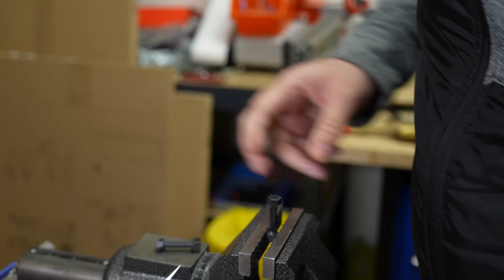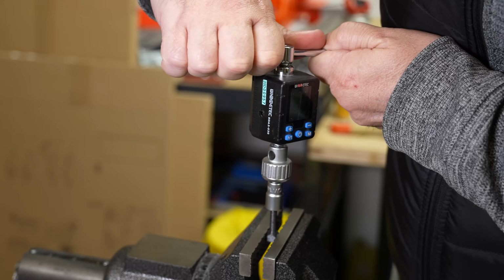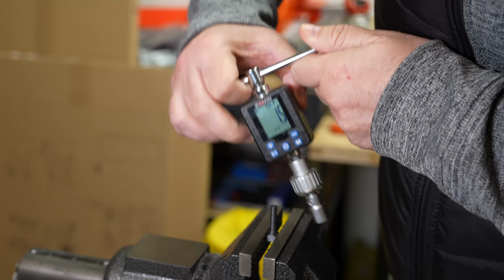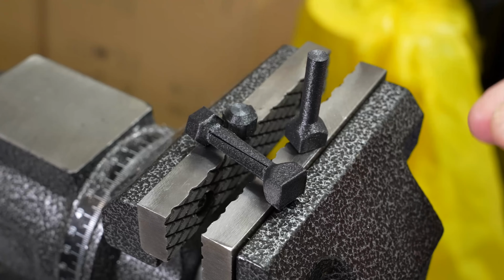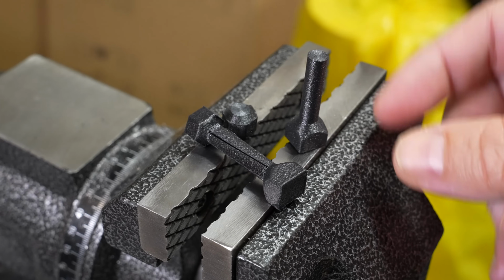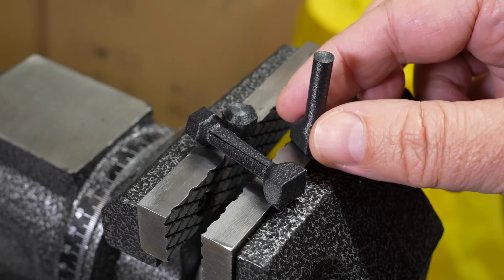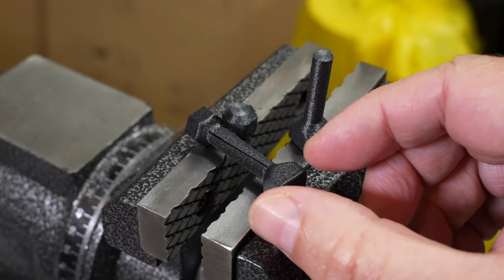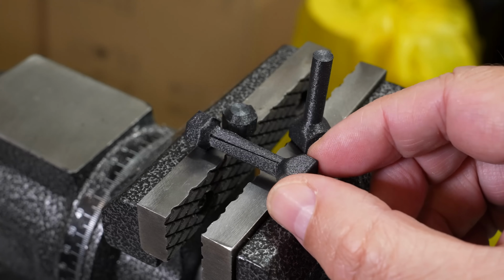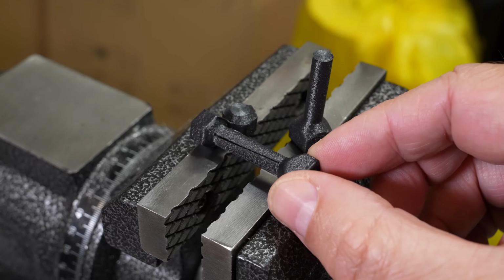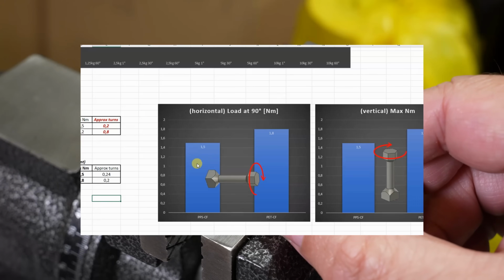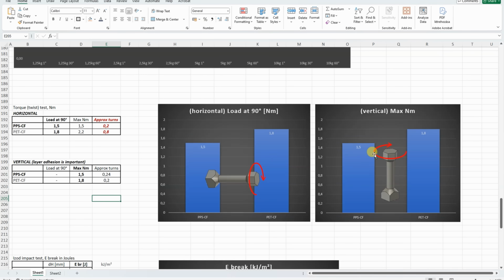1.5. Vertically printed, 1.5. I think both test objects are affected with this weaker layer adhesion. This one printed vertically directly, and this one printed horizontally. Can you see that gap? Weaker layer adhesion sometimes results also in weaker wall adhesion too. In both cases, PPS-CF is affected with that weaker layer adhesion, but I'm not reprinting these test objects, they go to the table as they are now.